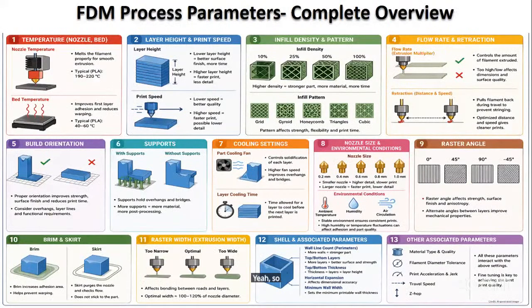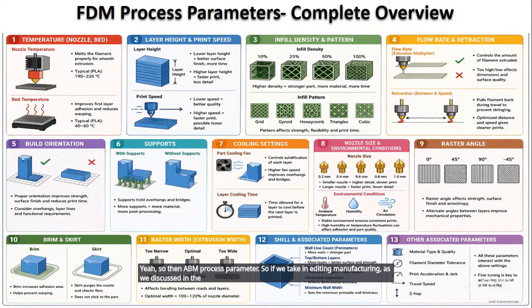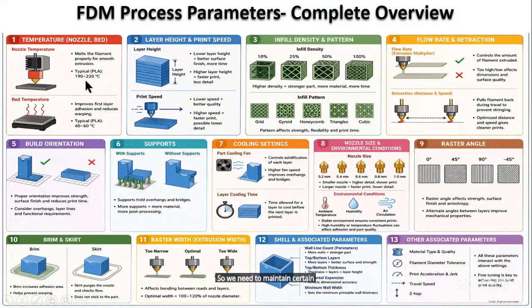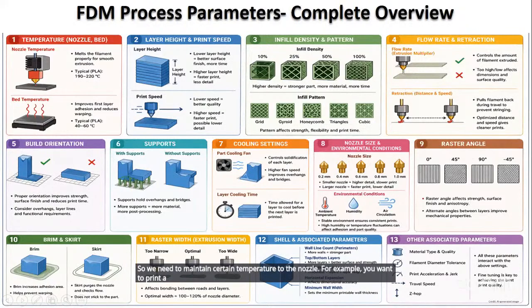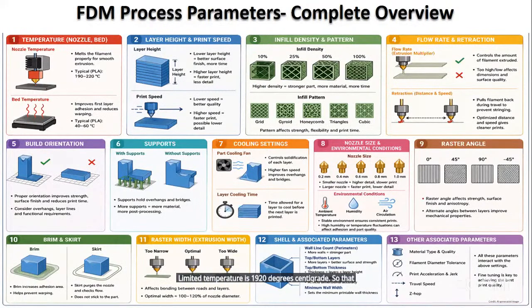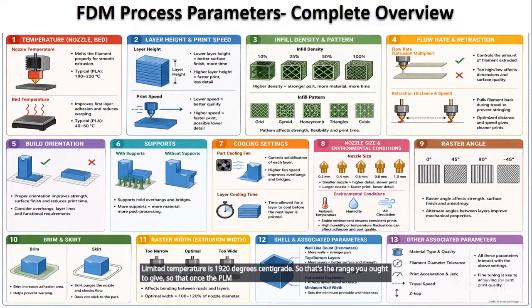Then FDM process parameters. In additive manufacturing, as we discussed in the classification, all machines have various process parameters. These are specific to the FDM machine, and we have the nozzle. A quick explanation: we need to maintain a certain temperature at the nozzle. For example, if you want to print PLA using FDM technology, the rated temperature is 190 to 220 degrees centigrade. That's the range you have to give, so that once the PLA material enters the rollers, it will melt and properly dispense onto the build plate. Bed temperature is also recommended at 40 to 60 degrees centigrade.